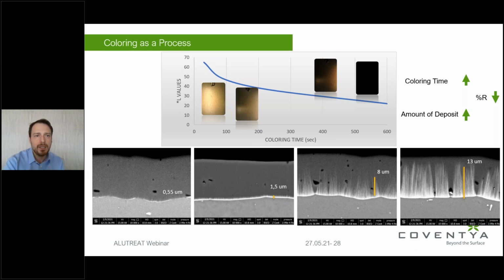And when we look a little bit more closely, what happens throughout your process is that here you can see on the left-hand side is the start of the process. So you have a minimum amount of tin. These belong to the tin sulfate-based electrocoloring process. So in maybe 30 seconds or 45 seconds, you have almost 500 nanometers, or 0.5 micron, thick tin precipitation, which is barely visible, and you have a very light color. As you can see, the L value of the color is around 65, so it's a light champagne.